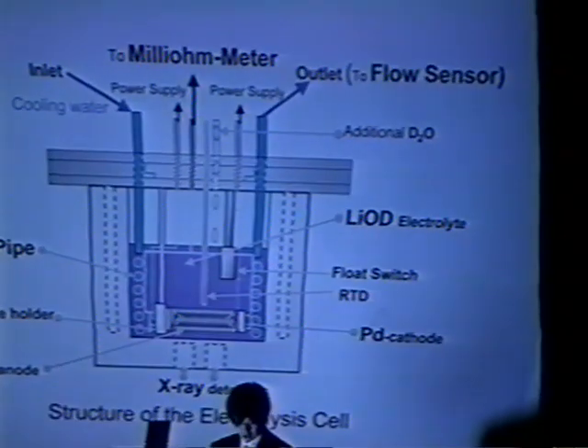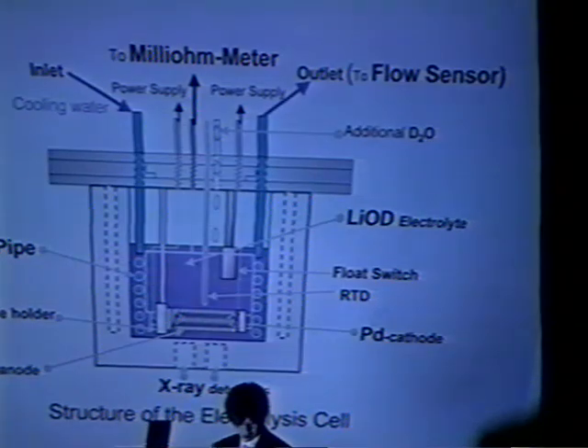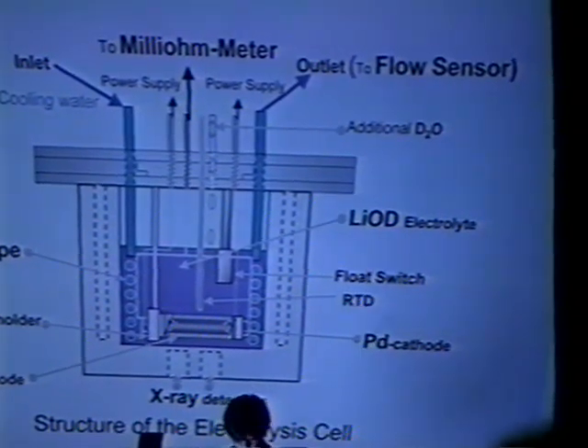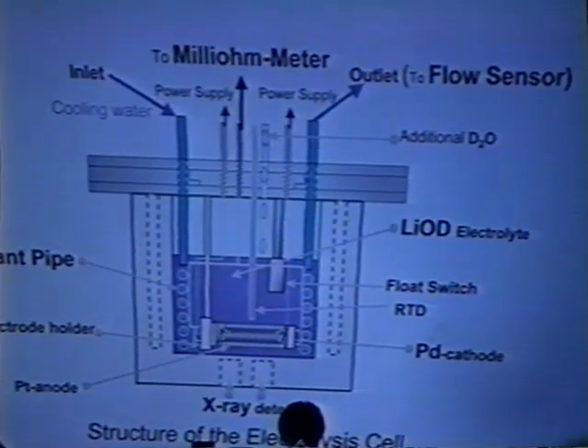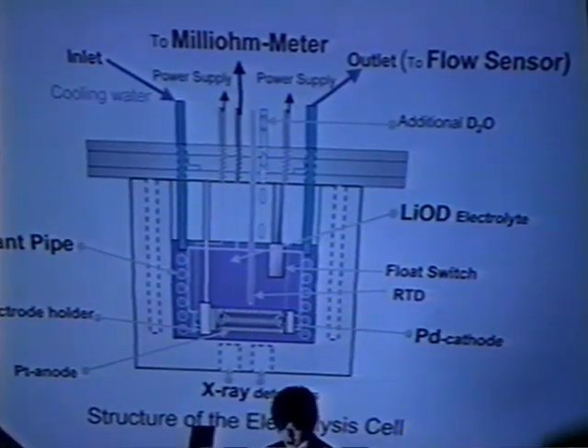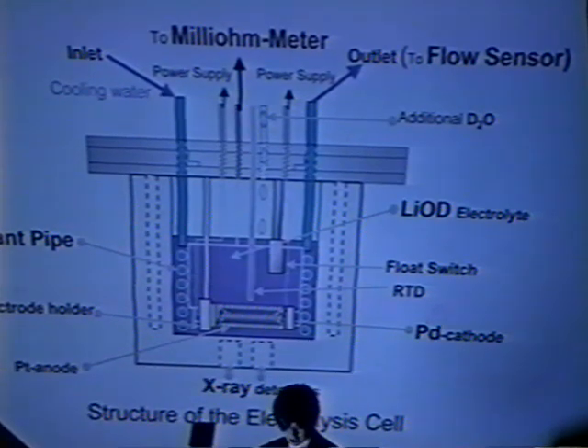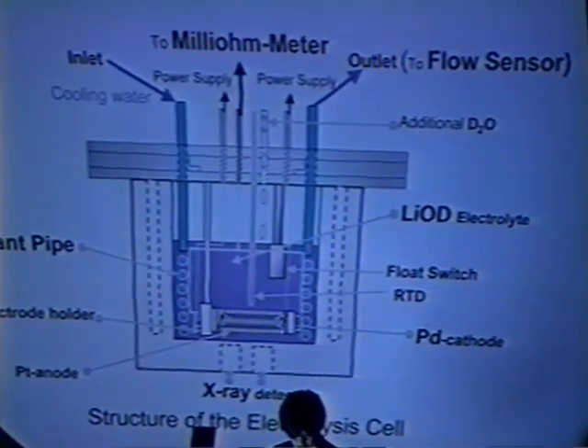This is the structure of the electrolysis cell. The electrolyte was LiOD. A coolant pipe was set in the cell so that heat produced in the cell was removed efficiently. The Pd cathode was set at the electrode holder. The temperature of the electrolyte was monitored by using this RTD. The degree of loading ratio was obtained by measuring the electrical resistance of the cathode with a meter and comparing it with the calibration data.